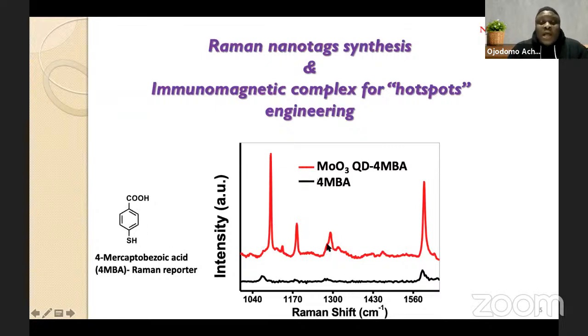So this is my work, whereby for 4-mercaptobenzoic acid, the Raman signal, as you can see, is not very distinct because of what I explained earlier: the normal Raman for a molecule tends to be quite small in intensity. But then we see, in the presence of molybdenum quantum dots, based on their plasmonic coupling with this 4-mercaptobenzoic acid, we're able to see an increase in the Raman signal.